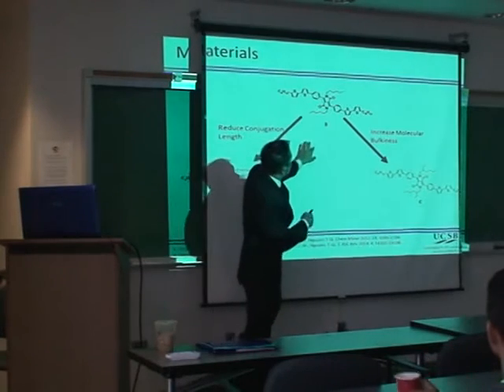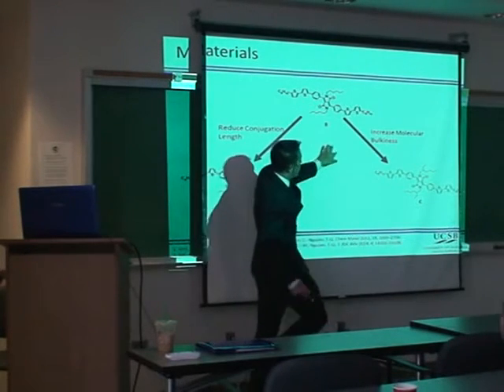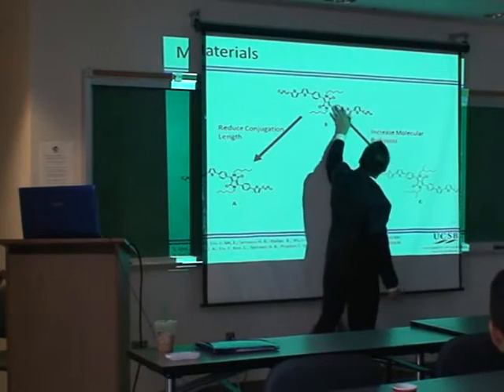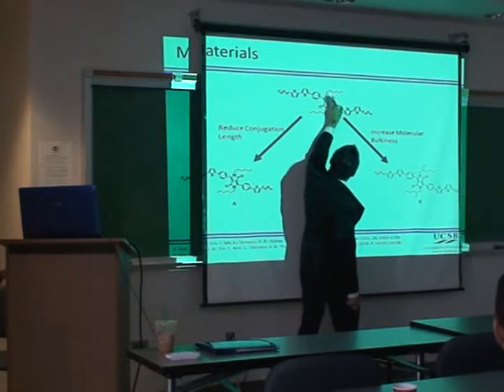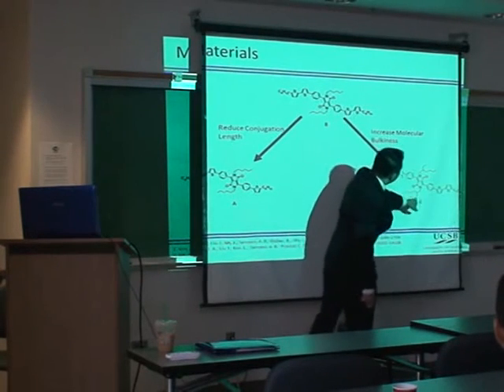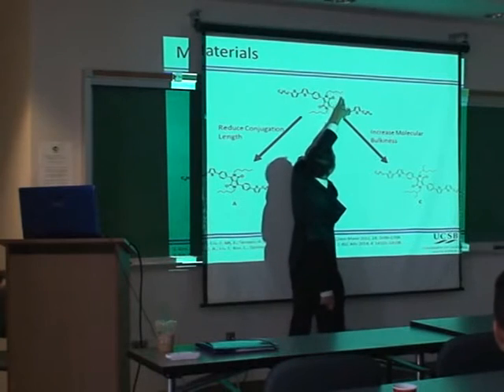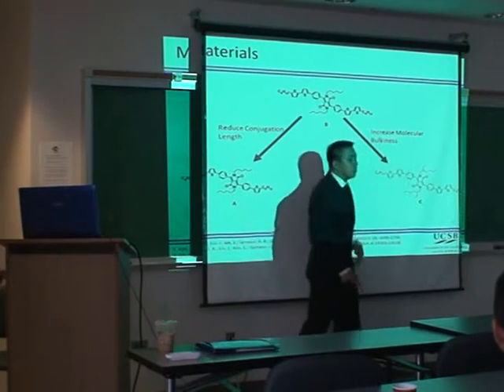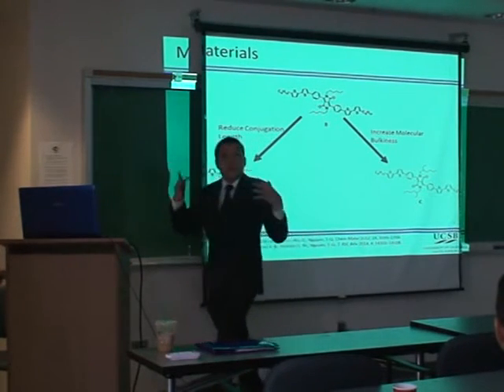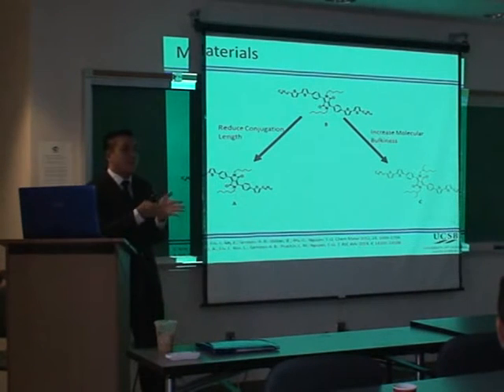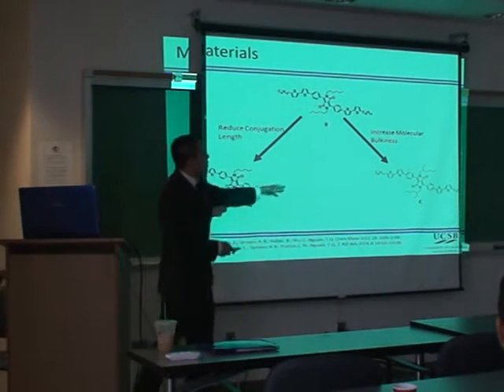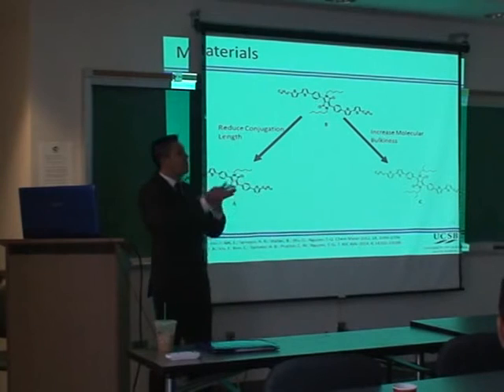In addition, I also studied how an increase in molecular bulkiness affects the packing. So the difference between the black structure, B, and C, is that we've converted the linear alkyl chains to a branched ethylhexyl group. And what this does is that it makes the molecule bulkier, and it prevents it from packing in the film. Therefore, this film is actually often amorphous. It is kind of randomly packed in a film.